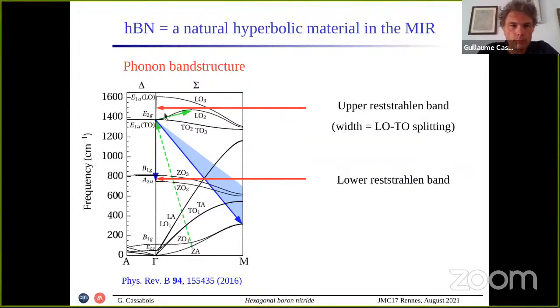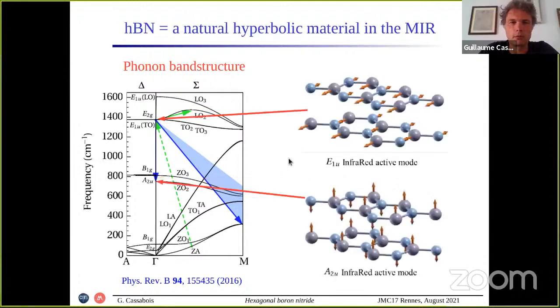If we want to visualize this a little more, I am plotting here the phonon modes, the transverse optical phonon modes. In real space, the atoms vibrate out of phase between boron and nitrogen. The neighbors are out of phase. This is a specific feature of optical phonon modes. But all the atoms vibrate in the plane.